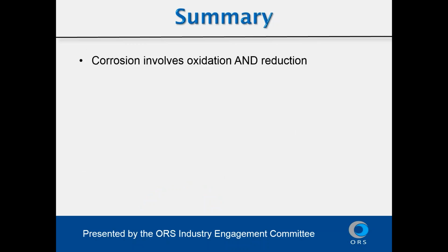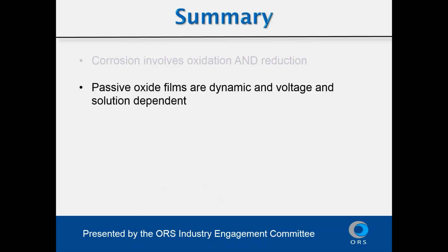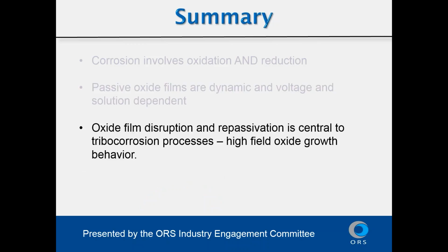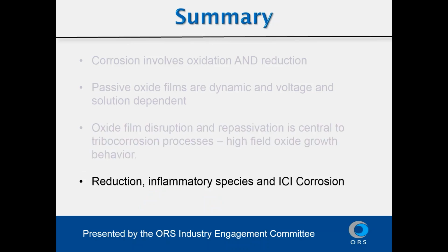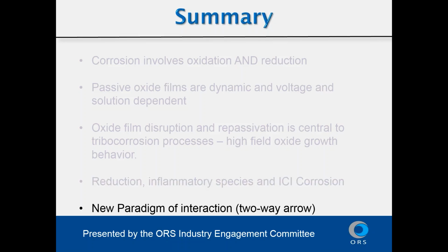And so with that, I'll summarize by saying that corrosion is both oxidation and reduction, that these passive oxide films are very dynamic and they're voltage and solution dependent, that we can model oxide film disruption and repassivation with some very accurate mathematical tools and engineering analysis tools that rely on the high field growth model for oxide films, and that finally both reduction reactions and inflammatory species that are generated by inflammatory cells can dramatically alter the nature of corrosion on these implant surfaces. And that finally we have this new paradigm of interaction that we need to consider when we design and build these medical devices and use these alloys.